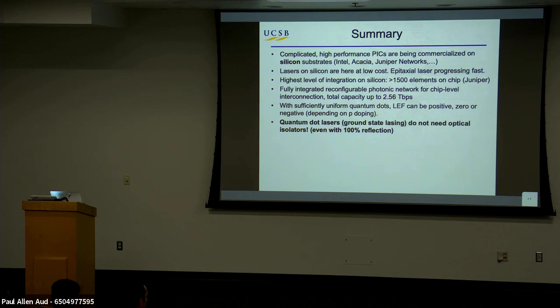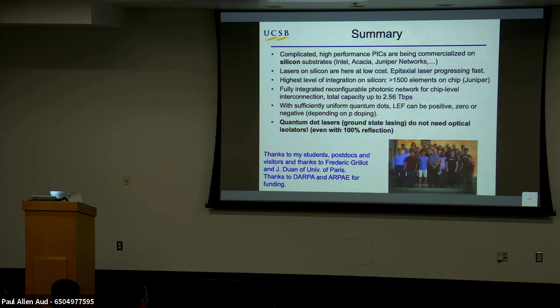And then I pointed out that if you make uniform quantum dots, you can make the linewidth enhancement factor 0 or slightly positive or negative. And consequently, you don't end up needing optical isolators, even with high levels of reflection. And it's just exactly what you'd expect from theory.